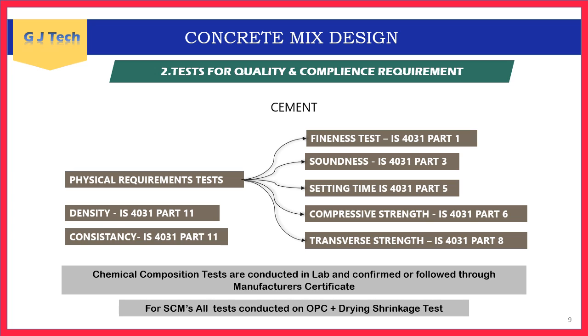For SCMs, all tests conducted on cement also apply. One additional test for mineral admixtures is the drying shrinkage test, because depending on fineness and surface area of SCMs, there may be increased shrinkage in fresh concrete. This limit must be confirmed in the laboratory before SCMs are used as cement replacement.